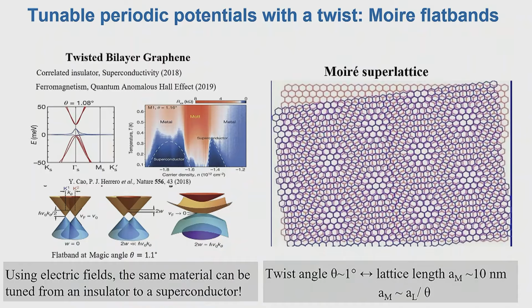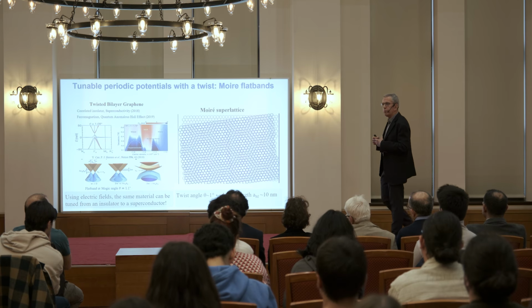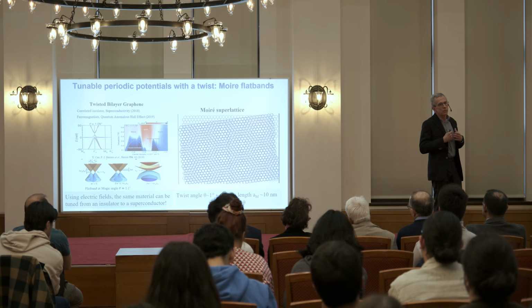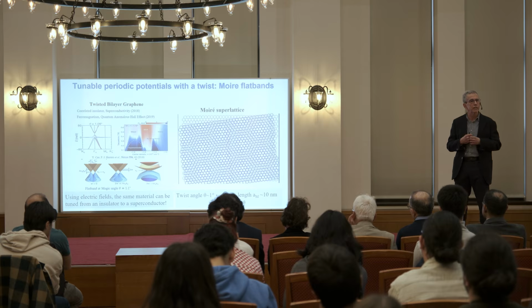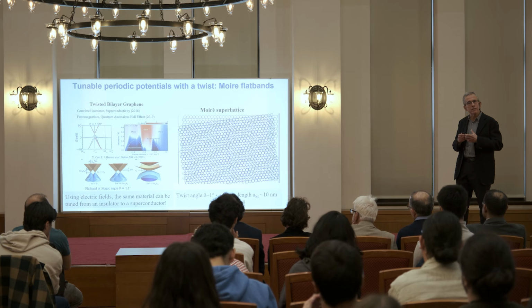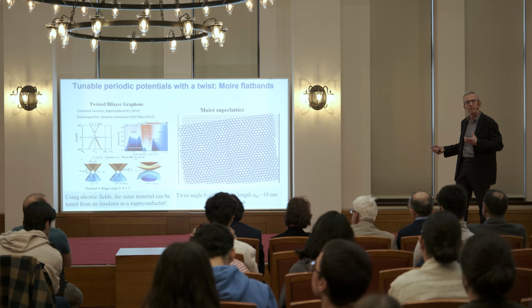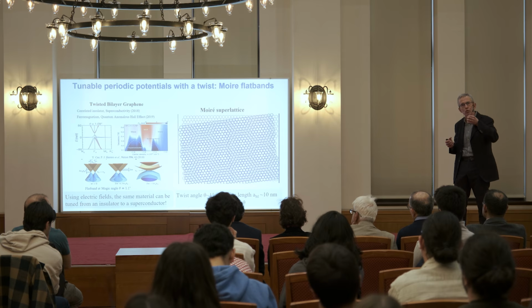And what they did then is to take this material, one material, and instead of trying to externally dope it, they applied a voltage, and this voltage allowed them to change the charge density and take the system from, let's say, in this case, a metallic state to a superconducting state, then to an insulating state, and to superconducting state, and so on. So in this way, the phase diagram that they obtained looked a lot like what the high-TC superconductors exhibit, with many different phenomena or properties existing within the same device and purely electrically tunable.